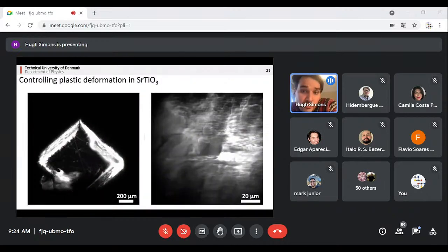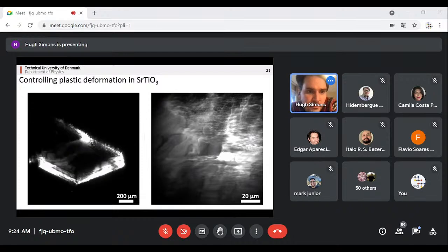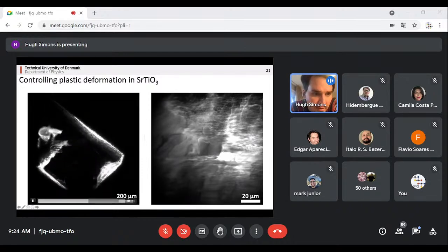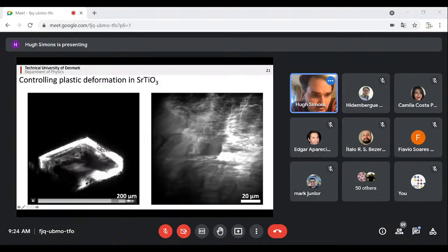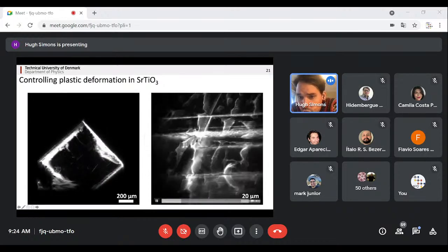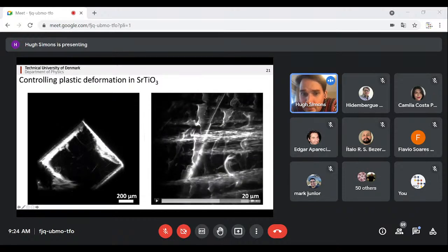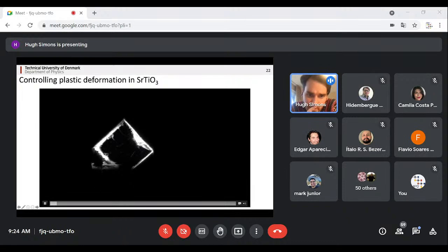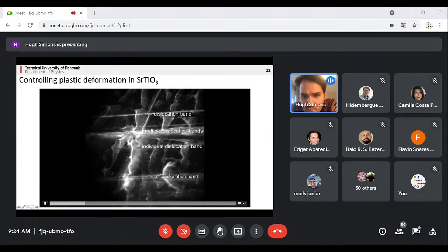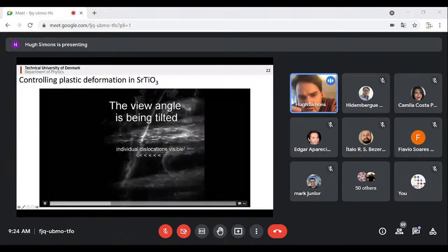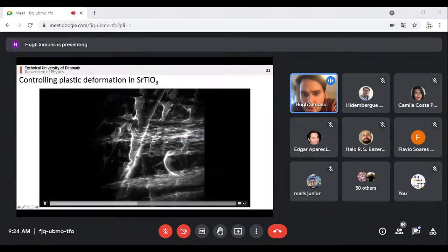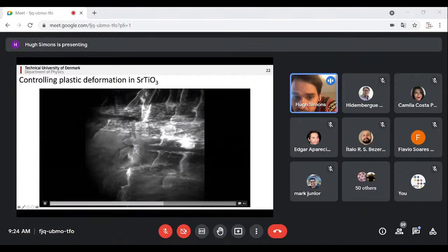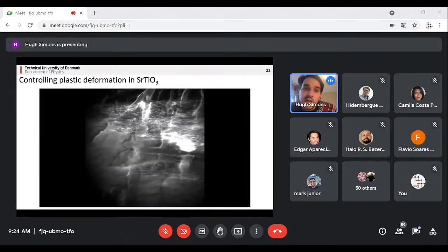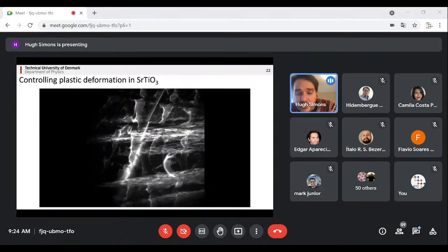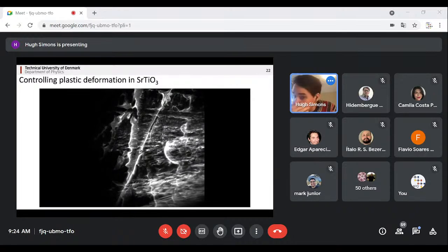So we used this topotomography technique again to visualize the sample, and you can see this is the outside of the sample, and there's deformation around the notch tip just in here. And then if we use our microscope, we can zoom in a little bit further and see how these are positioned in planes. To give you a bit more of a description, you can see that you form these individual dislocation bands. And as you change the viewing angle, you can actually see the individual dislocation lines running through the material. And so this data, in fact, allowed us to visualize exactly how these dislocation lines are bending and kinking as they pass through the materials and how they're interacting with one another. And this ultimately gives insight into the mechanism by which they form and the mechanism by which they enhance or affect the conductivity of the material.